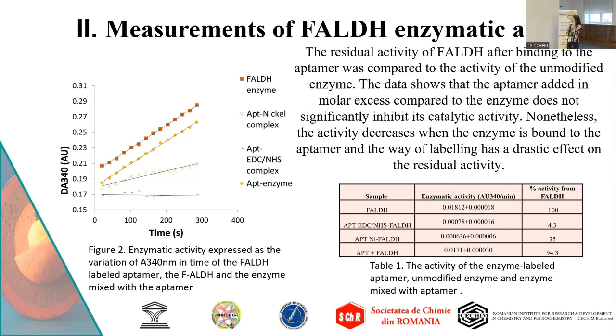And then we measured the enzymatic activity of the compounds. You can see that the compound with nickel chloride, our main compound of interest, retains a decent amount of enzymatic activity, around one third of the initial enzymatic activity, and the compound with EDC/NHS has almost no enzymatic activity, mainly because it affects the active sites of the enzyme.